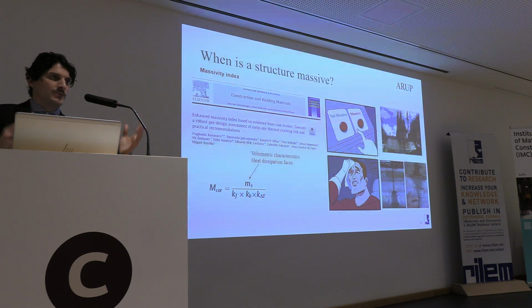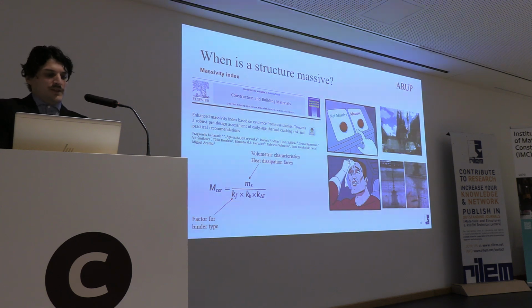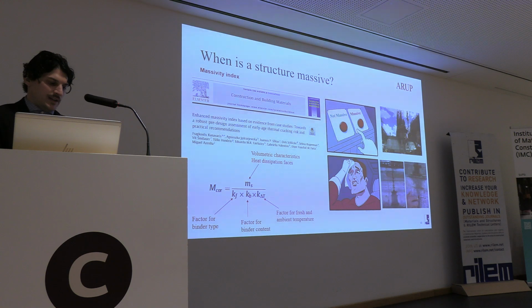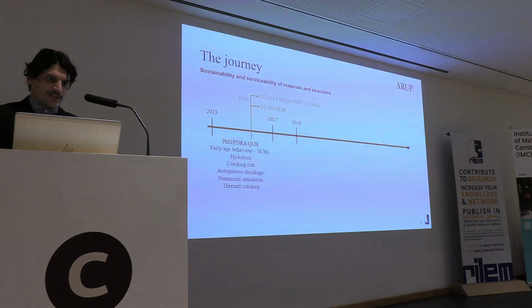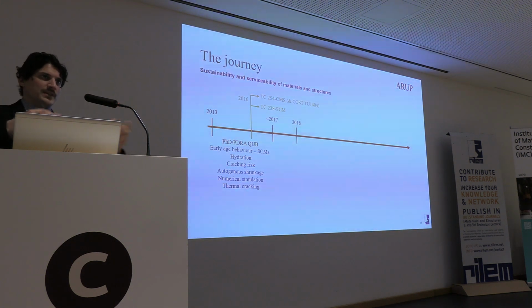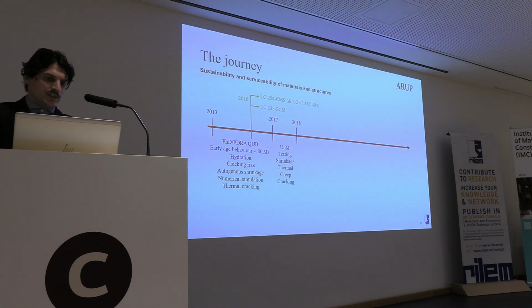It's about volume plus where heat can dissipate from, but also what type of binder is being used, the binder content, and the interplay between fresh and ambient temperatures. So around that time, because I developed this working relationship with the TC leads, I landed in University of Minho as a visiting fellow for a short period of time, and this was a really deep dive into testing for cracking, shrinkage, thermal creep, and creep effects.